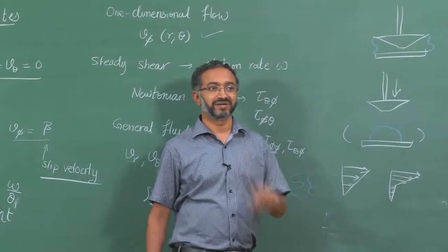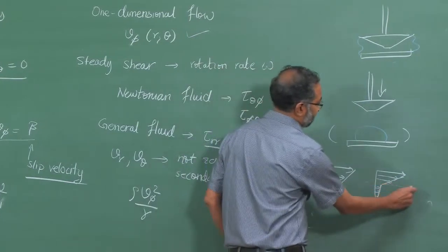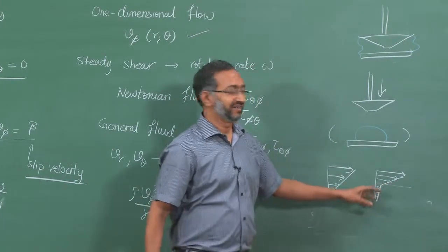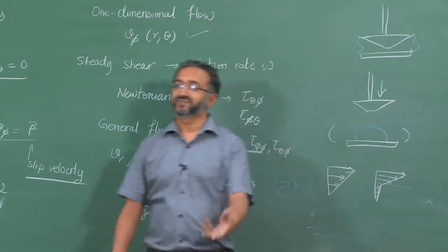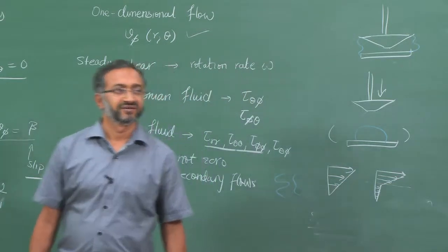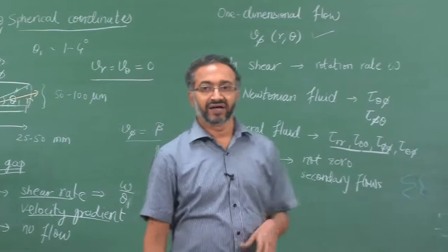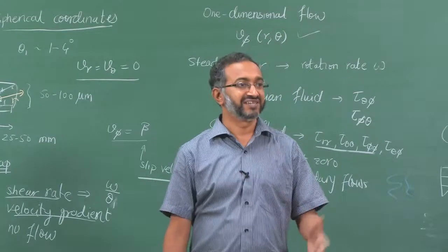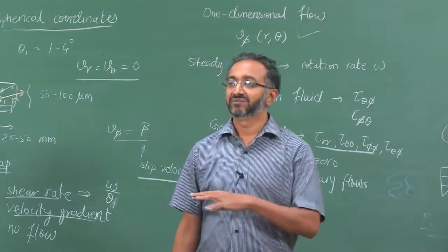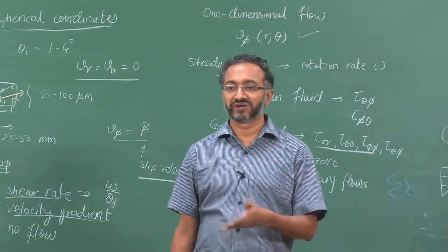So two bands appear, one band in which the shear rate is very low and one band in which the shear rate is extremely high. And again, this is a very interesting phenomenon which has been observed for many materials, and visualization is of course always the easiest way to characterize it, but not all materials can be visualized.